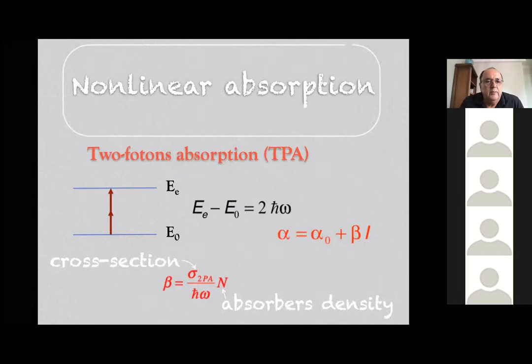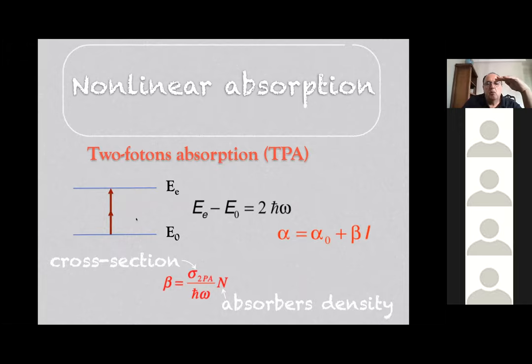Well, when we speak about nonlinear optical absorption in materials, the idea is very simple. If you have a steady ground state of your electron, for example, and the first excited state is here, and the amount of energy in your photon is not enough to take one electron from the ground to the first excited state, what happens with a high intensity laser shining on the sample is that your electron will absorb two photons.